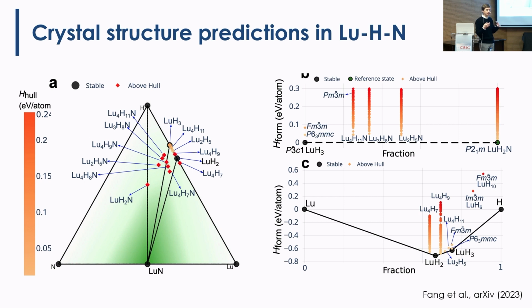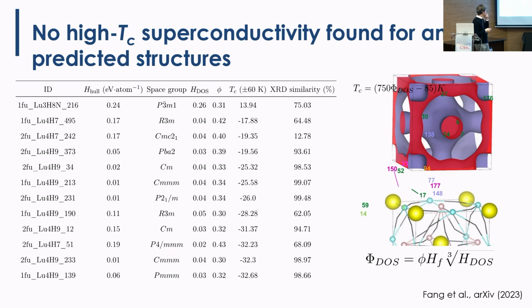These are not the structure. So we did crystal structure predictions, also including nitrogen. We did it for lutetium H2 and lutetium H3. I mean, if you draw a line, you expect something in between, but it's maybe not the truth, obviously. So then we added nitrogen and we did crystal structure prediction. So this is the energetics, okay, a big mess, but many compounds that we analyzed, and there is something that we did here, okay.